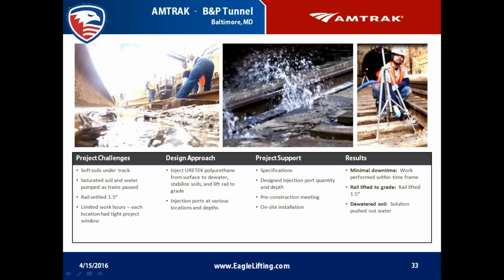But we were able to inject the URETEK polyurethane from the surface to dewater and stabilize the soils, and then lift the rail back to grade. The injection ports were at various locations and depths. Working with Amtrak, we were able to get minimal downtime because all of the work was performed within that small window we were discussing, to keep the downtime of the trains that passed through that area down to almost 0. The rail was lifted a full 1.5 inches up to grade, and as I was mentioning with the freeways earlier, when you're injecting, you can actually watch the water being pumped out while the injections are occurring. So during the injections here, you were able to see the water being pushed out, and since then, Amtrak has not experienced a problem of water infiltration or settlement in this area.